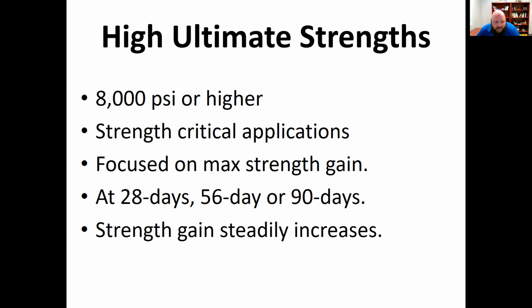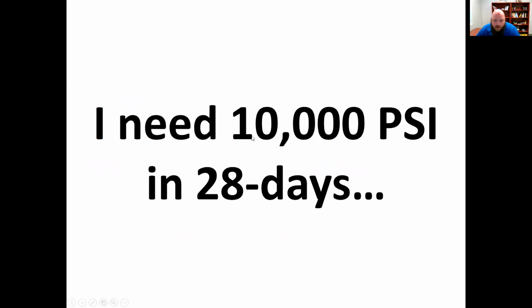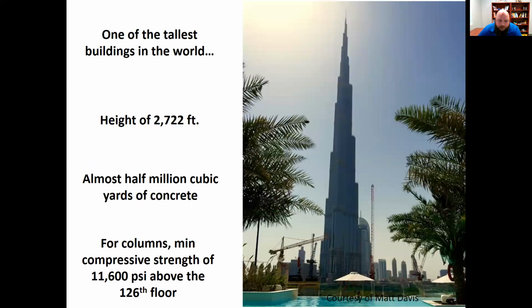Typically, when we talk about the ultimate high strength, again, it might be at 28, it may even be 56 or even 90 days, just so that we have enough time so the concrete can properly gain strengths. So it's all about that maximum gain. And we're focused on having a nice steady increase. Typically, if you have it all start in the beginning, it can plateau out really quickly. So we're more focused on a strength gain that's steady over time. All right. So maybe you hear things like, I need 10,000 PSI at 28 days. Well, that would be ultimate high strength concrete.